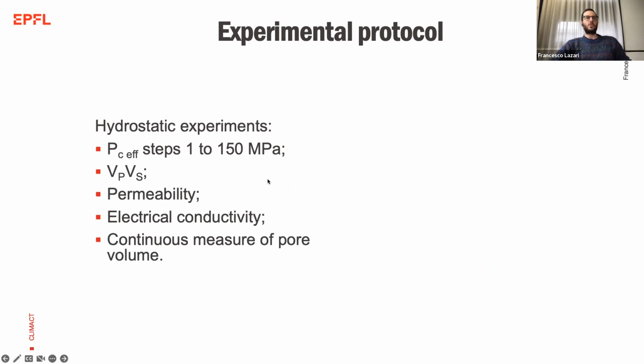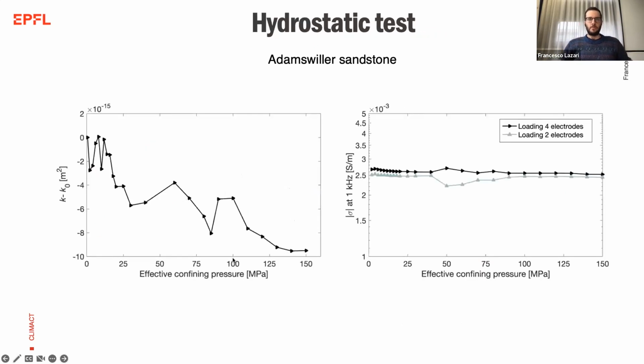We did some pressure steps from 1 to 150 megapascals. And at each step, we measured the seismic velocity through the sample, the permeability, the electrical conductivity, and we had a continuous measurement of the volume of the pores during the experiment. Here is one of the experiments that we did.